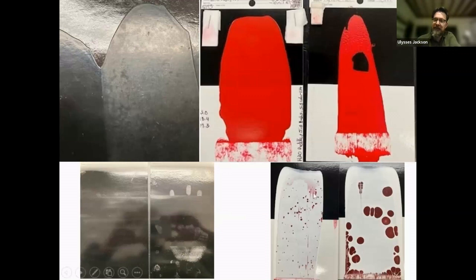And then this one is looking at surface energy differences. This would be the red iron oxide, the PR 101 coating underneath that was wet. And while it was still wet, we drew another thinner white coating over top. And we can see these kind of lava lamp patterns forming where the surface energy is reduced underneath. And so it's pushing off the paint over top, or crawling. So we have to look out for that inner layering.